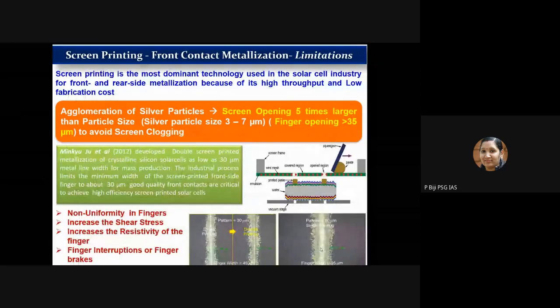During this screen printing process, agglomeration of silver particles has been observed. The screen opening should be 5 times larger than the particle size. Therefore, the silver particle size should be in the range of 3 to 7 micrometers, and a finger opening above 35 micrometers is required to avoid screen clogging. So that's one disadvantage, because when you go for narrow line width, reducing the silver particle size is another challenge. That is something you have to think about.